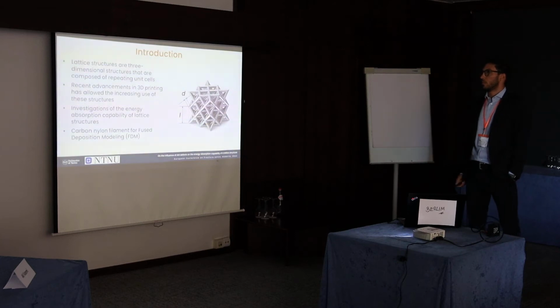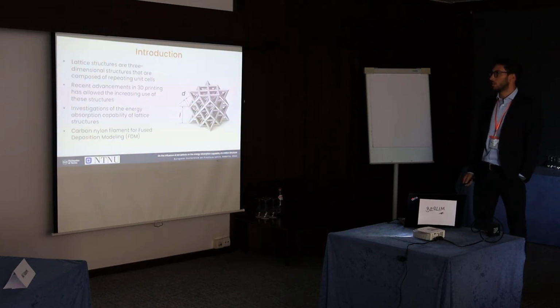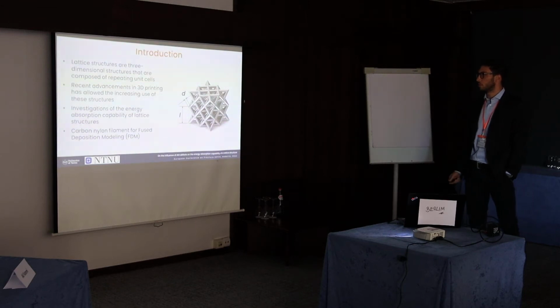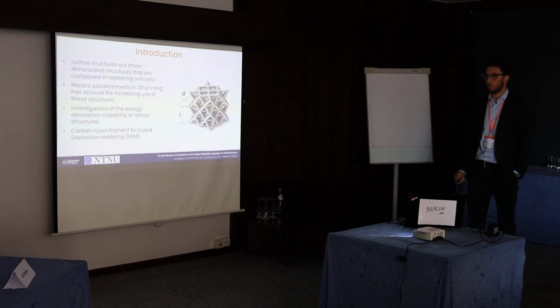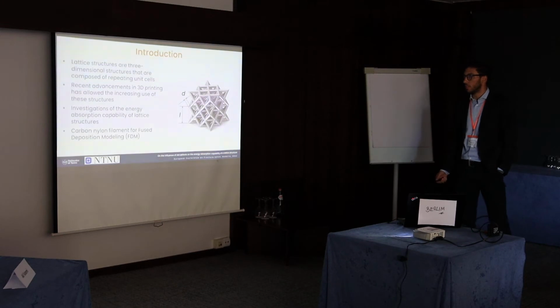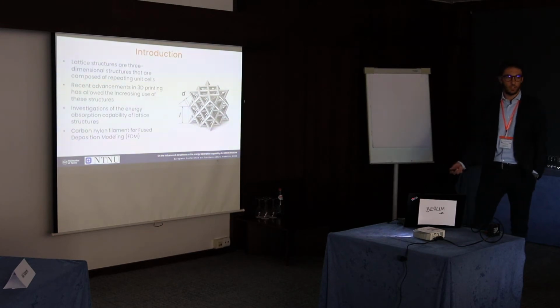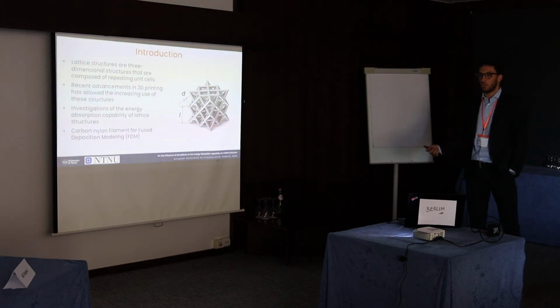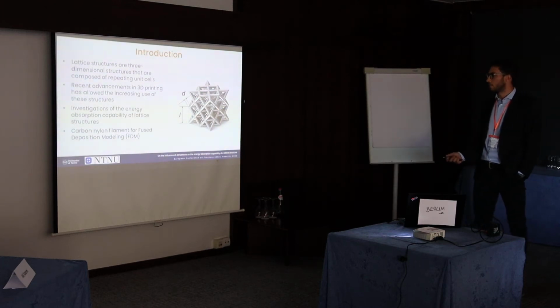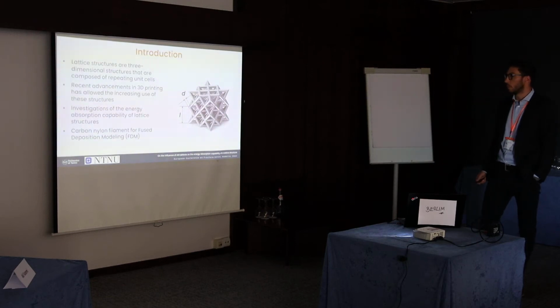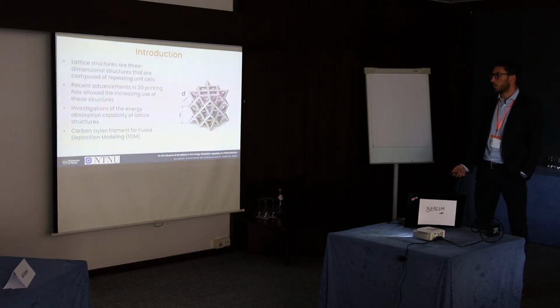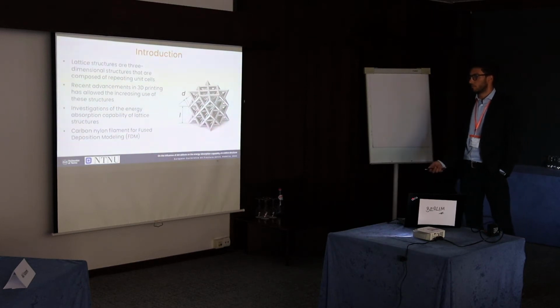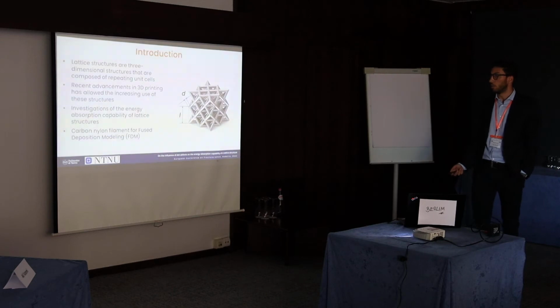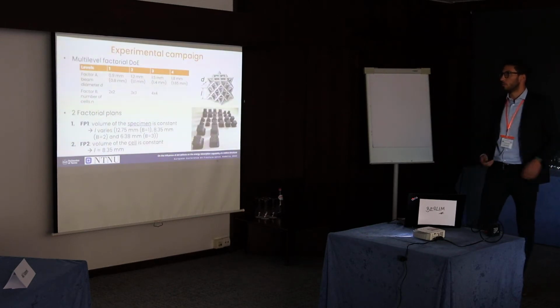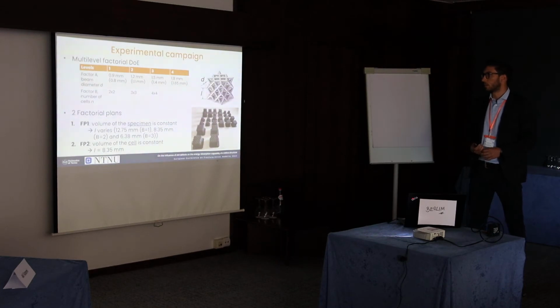So for those who are not familiar with the topic, lattice structures are three-dimensional structures that are composed of repeating unit cells. And the recent advancement in 3D printing has allowed the increasing use of these structures. So we started investigating the energy absorption capability of several different lattice structures. And among them, we identified this one as the best performing in terms of energy absorption. In particular, this one was made from carbon nylon filament and produced with fused deposition modeling. Then we performed a more extensive experimental campaign on this lattice structure.